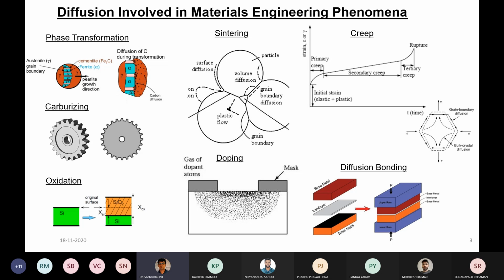If nanocrystalline grains are there, then what is going to happen? Nanocrystalline means at least one dimension of the grain must be less than 100 nanometers. So a very small grain size can help you get high strength as per the criterion of decreasing grain size. You get high yield strength up to a certain point as per the Hall-Petch equation. But at high temperature, what you get is a high volume of grain boundary. And if it is beyond the equicohesive temperature, then what is going to happen? Grain boundary is weaker than grain. So in that temperature regime, if deformation is occurring, then grain boundary diffusion, lattice diffusion, all the processes are going to play a very strong role.